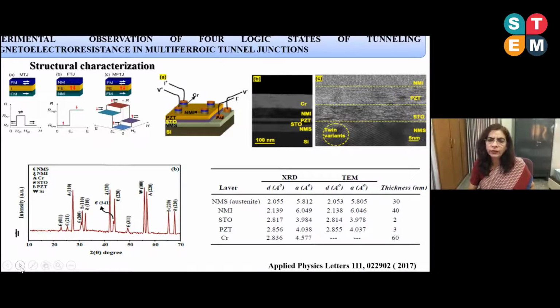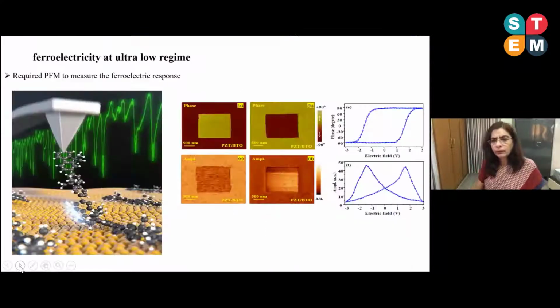We have also an antiferromagnetic chromium layer of 60 nanometers. This device was fabricated using the magnetron sputtering technique, and this shows the cross-sectional FESEM image of the layers. This is a kind of memory device structure.